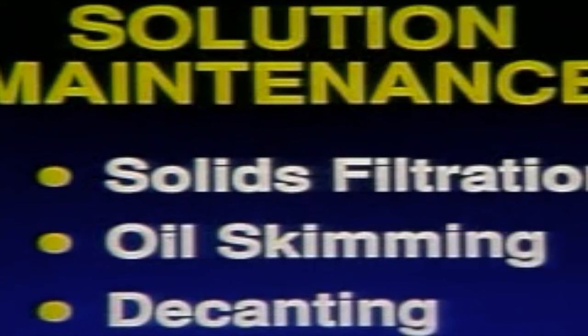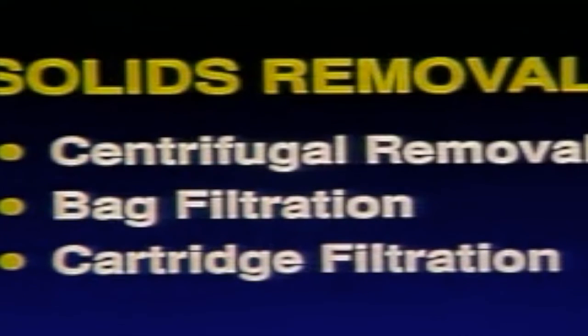As was mentioned earlier, keep tramp oils skimmed off cleaner and rinse stages. This prevents oils from being redeposited on the part and helps prolong bath life. Consider filtration of the cleaning and phosphating baths to reduce sludge and metal fines. This helps keep risers and nozzles from plugging, and it extends the bath life.